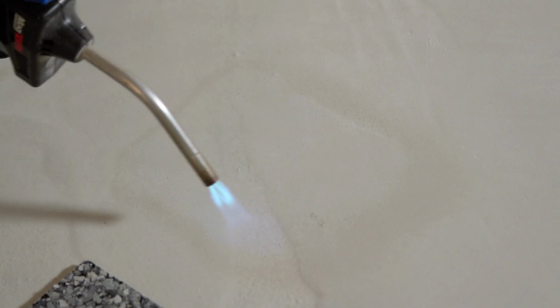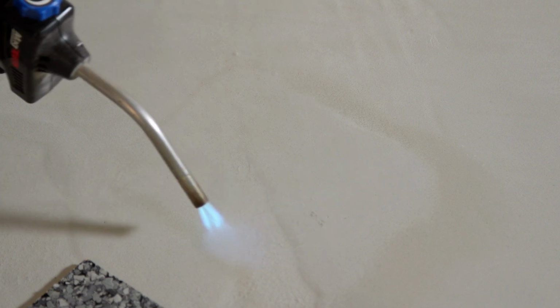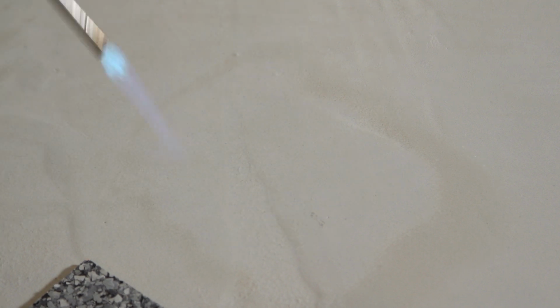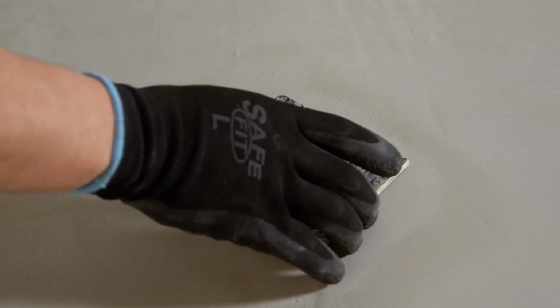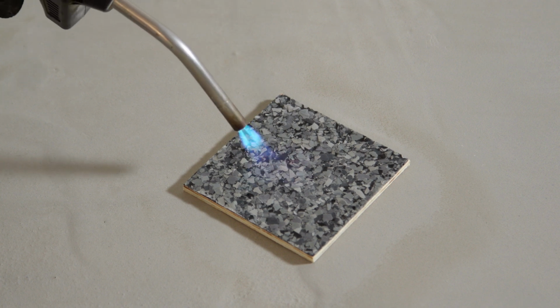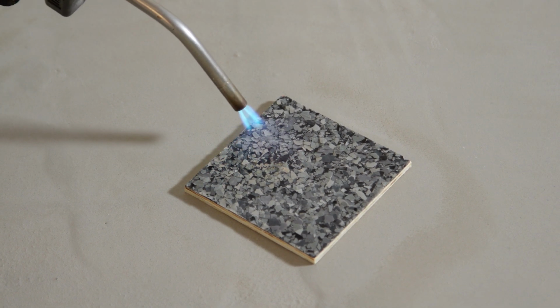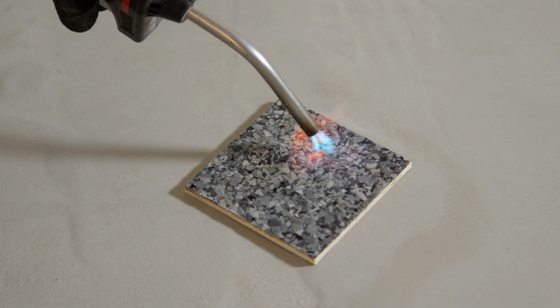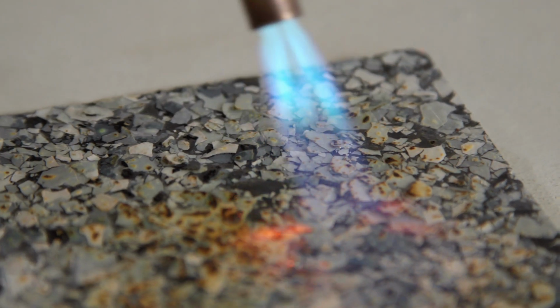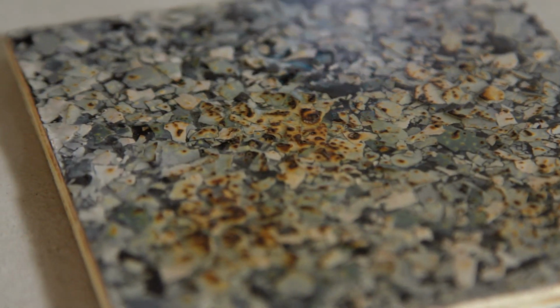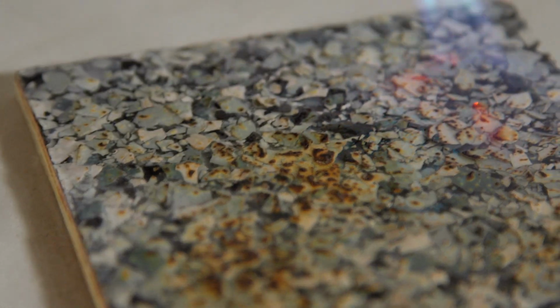You can see the blowtorch isn't affecting the urethane cement at all. And then if we go ahead and place our epoxy sample in there and take it, you can see how quickly it's bubbling the coating. As you can see, there's a huge difference in performance against the heat between the two samples.